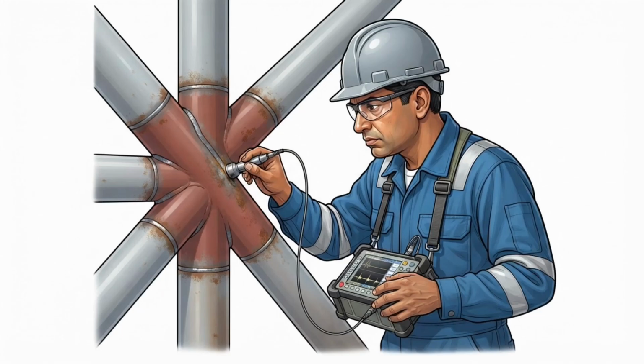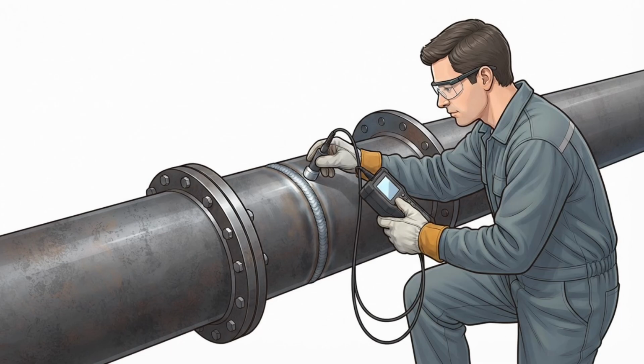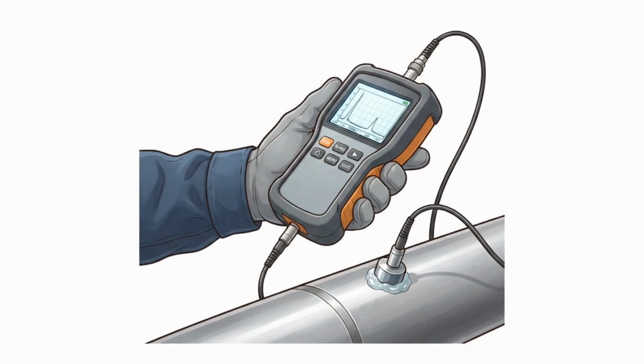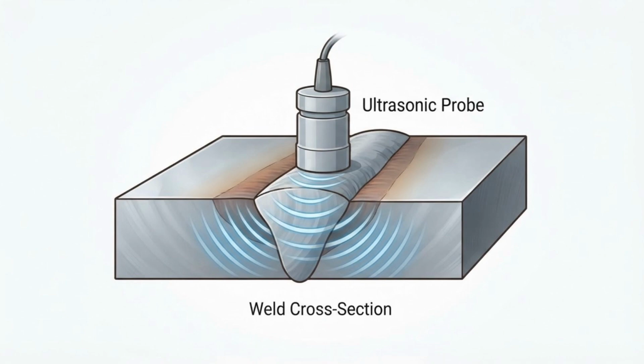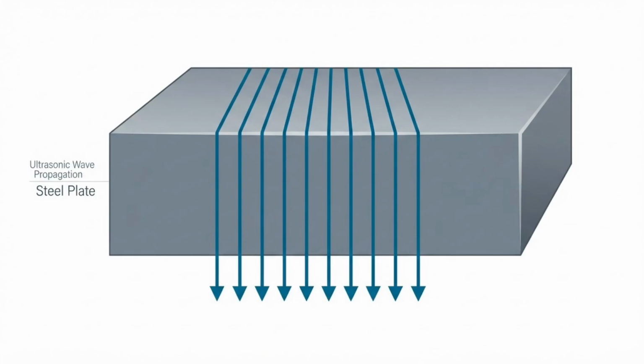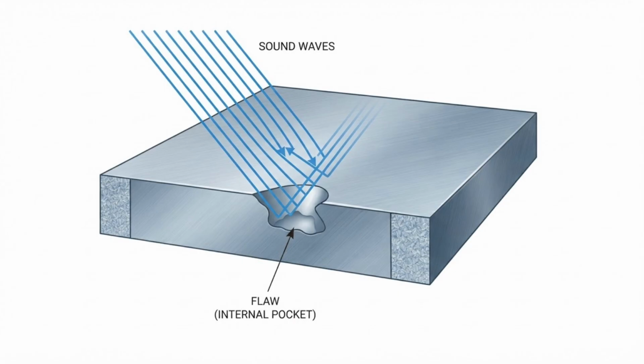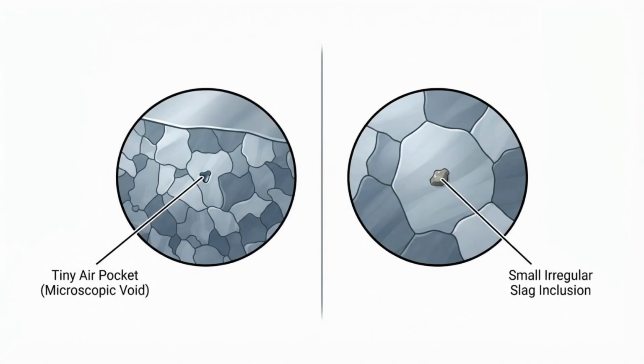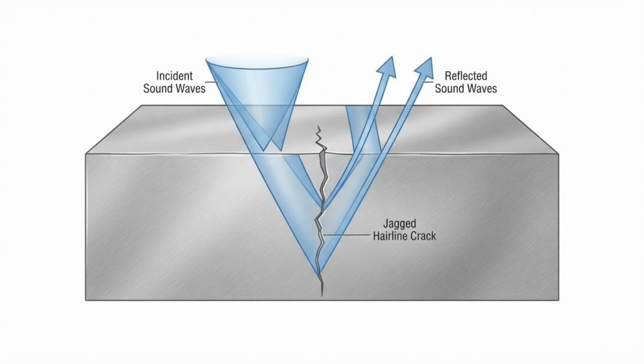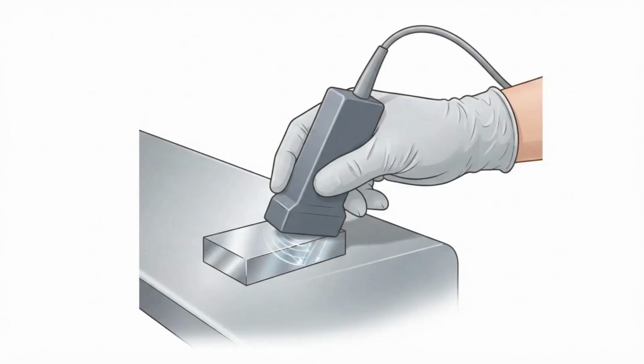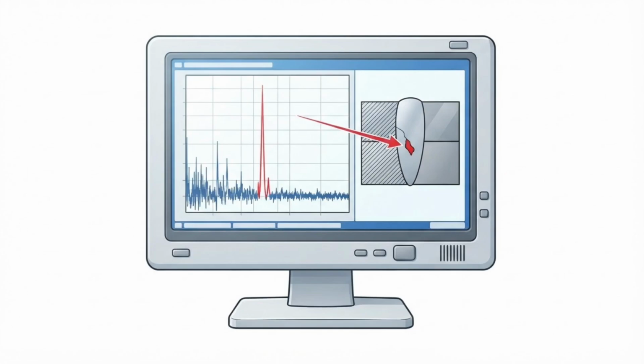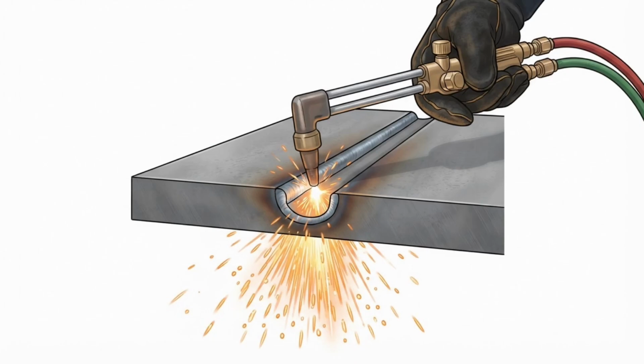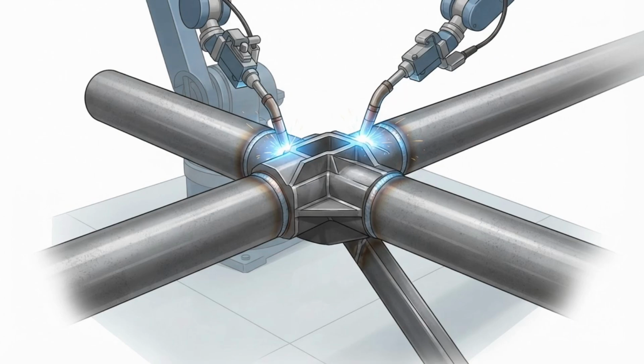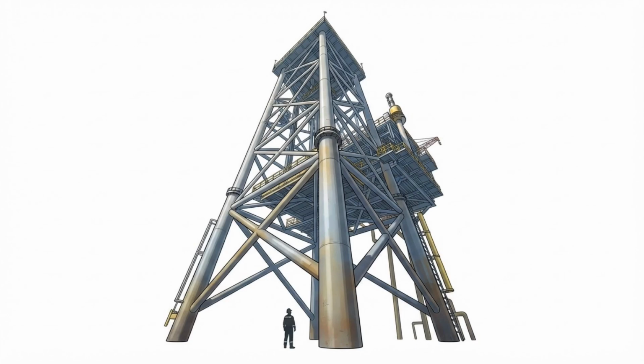To guarantee that the structural integrity is flawless, every critical weld undergoes rigorous non-destructive testing. Technicians use phased-array ultrasonic testing devices, which send high-frequency sound waves deep into the solid steel. If the sound waves hit an internal defect, like a microscopic void, a trapped piece of slag, or a tiny hairline crack, the echoes bounce back to a receiver, mapping the invisible flaw on a digital screen. Any imperfect welds are immediately gouged out and completely remade. As the tubulars and nodes are welded together, the structure grows to the size of a skyscraper.